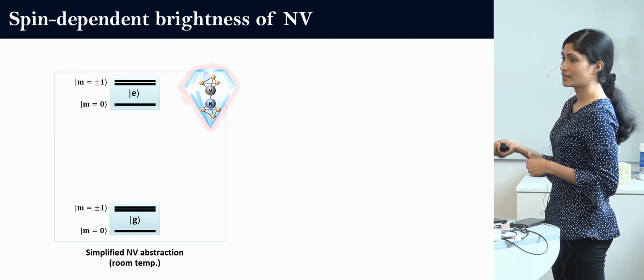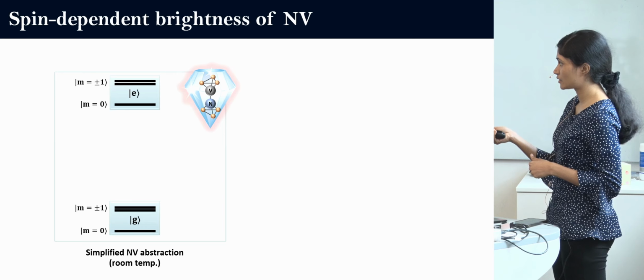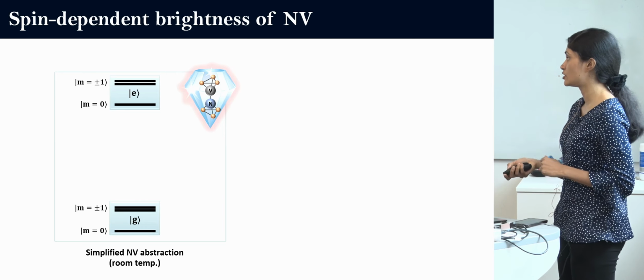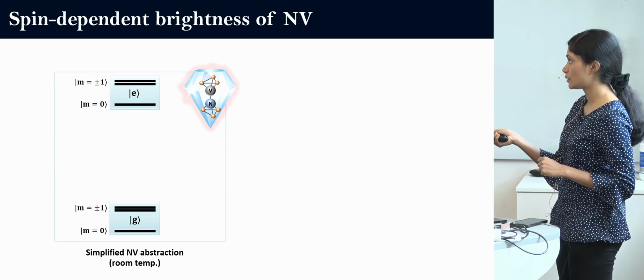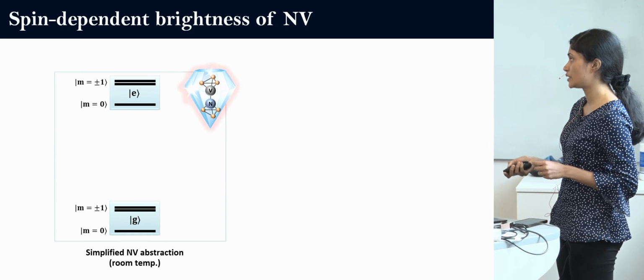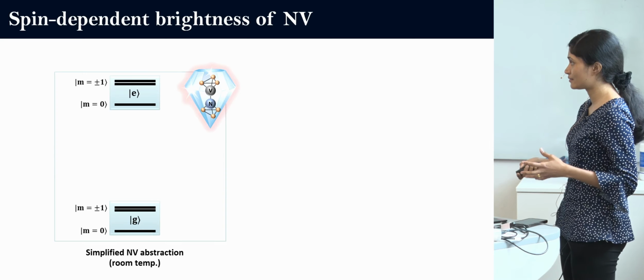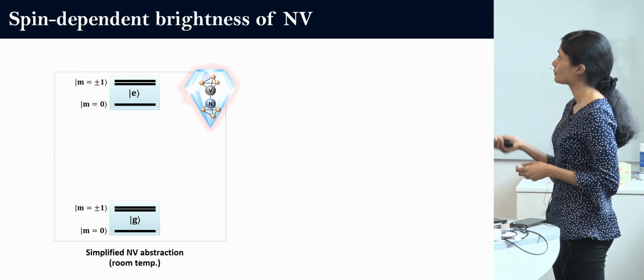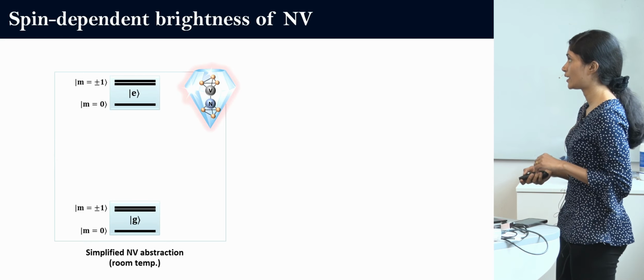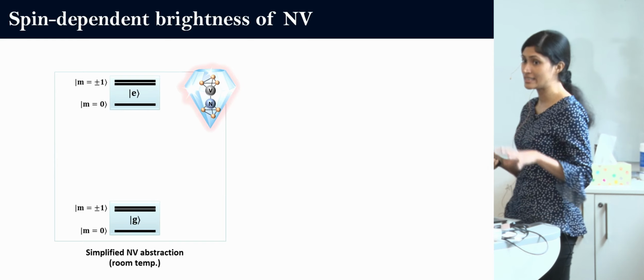So let's assume that the NV center has an optical ground state G, which is a spin triplet comprising the states that we just discussed, the spin 0, +1 and -1, and +1 and -1 are usually degenerate if nothing is disturbing the NV center too much. And again, the excited optical state has the same 3 spin levels, at least in the ground state.